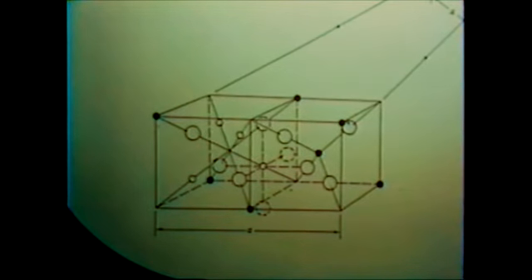And to go further, a lot of these properties are known. For example, the magnetic coupling. If you have magnetic ions on these sites, the magnetic coupling between these ions is all the time negative. Whether it's inter or intra sublattice coupling, they are all negative. But the stronger coupling is between the A and B. So if you have a magnetic ion on the A side and the B side, you will have the stronger exchange interaction, the stronger magnetic interaction. And then you force the magnetic ions on the B sides to be up, because you cannot have all of them negative, and you force the one on the A side to be down. Only the AB will be up and down.